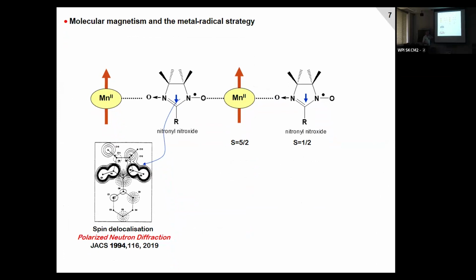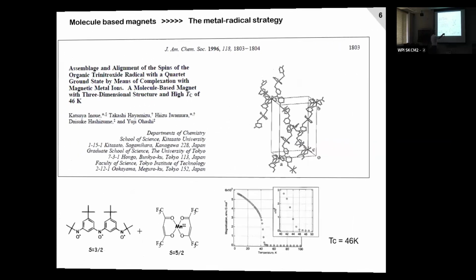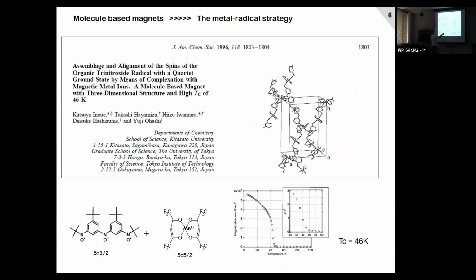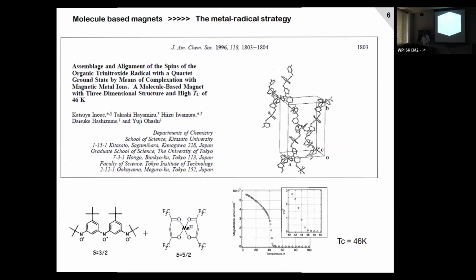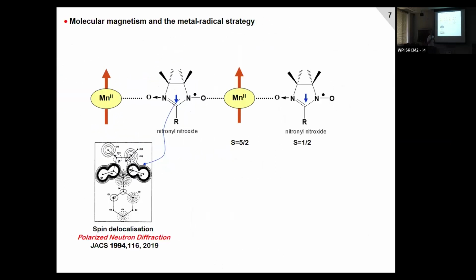In fact, from the chemical point of view, the NO group is a weak Lewis base. So it is very difficult to coordinate to metal ions. Generally, we use this kind of complex because the manganese 2, when it is surrounded by hexafluoroacetylacetonate, becomes very acidic. And in that case, it's easier to connect with the NO group, which is a weak Lewis base. But if you do this, finally, the only thing you can make are chain compounds. But chain compounds are not enough if you want to have a magnet. If you want to have a magnet, you have to connect the metal ions in the 3 directions.